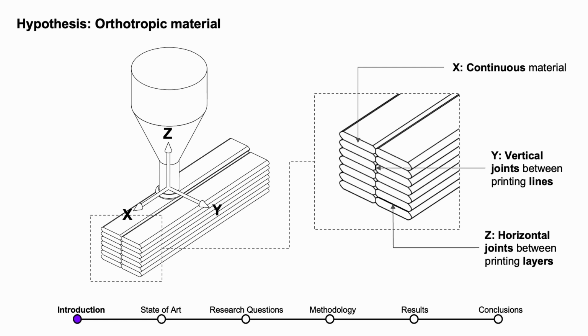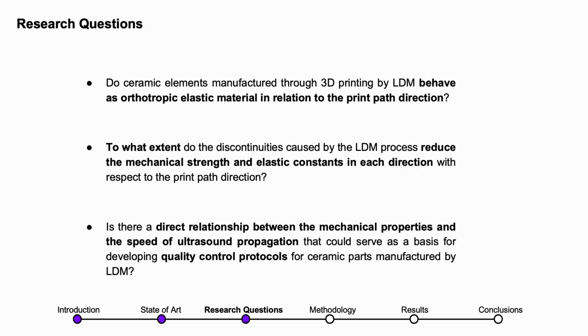In the X direction, we have a continuous material because it is the printing direction. In the Y direction, we're going to find these vertical joints between the printing lines. And in the Z direction, the horizontal joints between the printing layers. So our research question is whether the material actually behaves as an orthotropic elastic material, and to what extent. Also, we're going to carry out ultrasonic, non-destructive tests to see if there is a direct relationship between the mechanical properties and the speed of ultrasound propagation for this material, which could serve as a basis for developing a non-destructive quality control protocol.